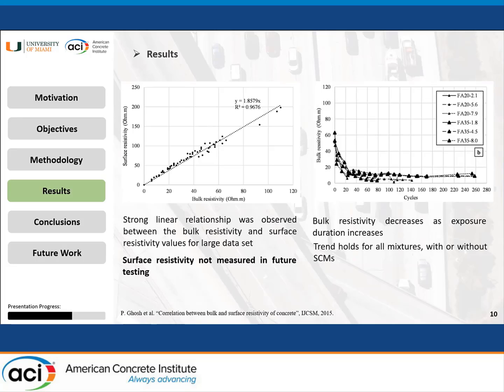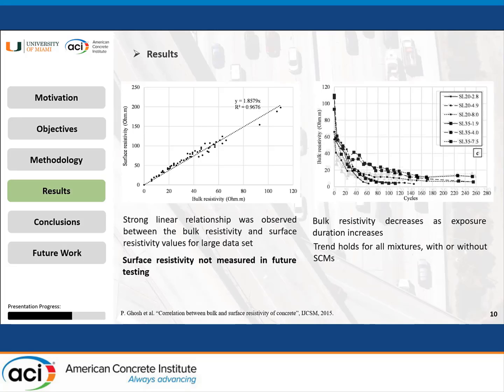The same case for the samples containing fly ash with different amounts of air, the trend holds for all of the mixes, whether they have the SCM in them or not. And it's the same case with the samples containing slag in them. And as noted, the initial resistivity was affected both by the air content as well as the SCM type and their portion in the mix design.